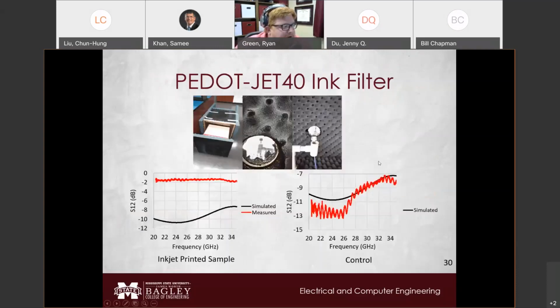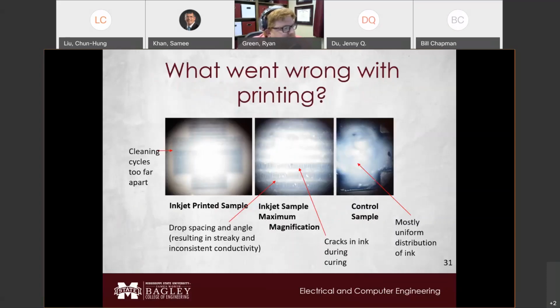And we put it through the test, and what we found is that our control was actually operating a lot better than our inkjet printed sample. So again, another challenge, because our expected results essentially showed that, hey, everything's passing through, when it should be blocking something. What gives? Well, we dug a little bit deeper and took a look at how the thing was actually printed. There's a couple of things going on here.